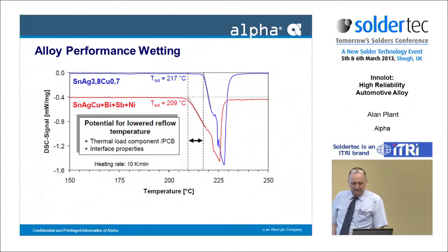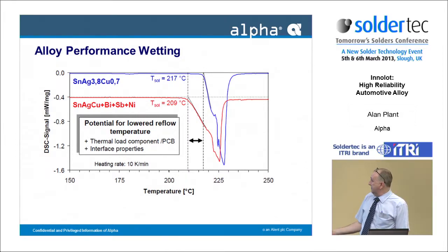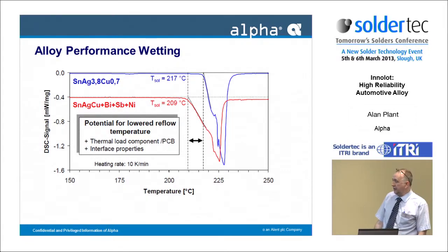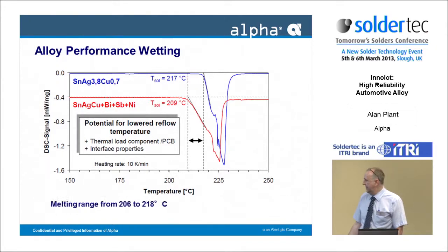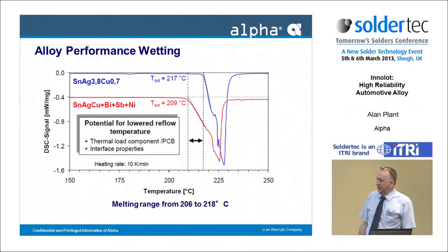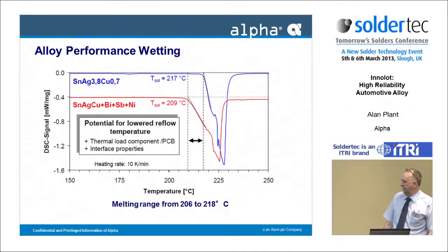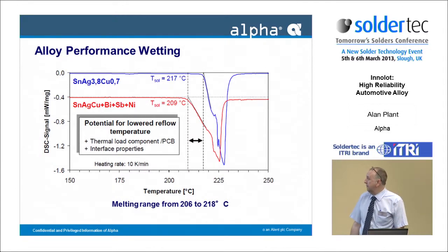We've got an alloy. What do we know about it in terms of wetting performance? One of the targets was to get an alloy that you could use at a lower temperature. And with the DSC plots, you can see that the solidus has shifted by about 8 degrees. It's interesting, how many thermodynamicists does it take to agree on a melting point? I think most of the people who supply the alloy say the melting range is around about that at the moment, taken to be somewhere about 206. So, depending on the heating rate, etc., there's a little bit of a shift, but there you go.